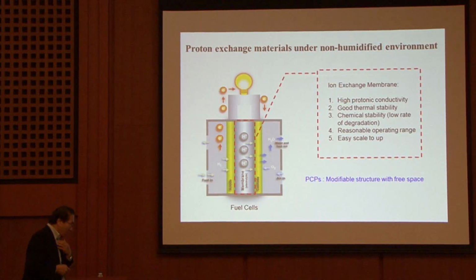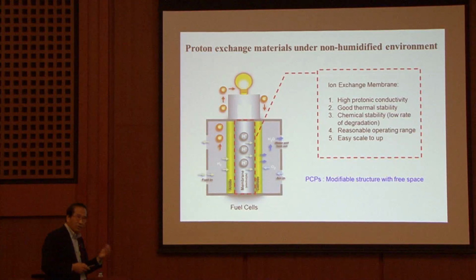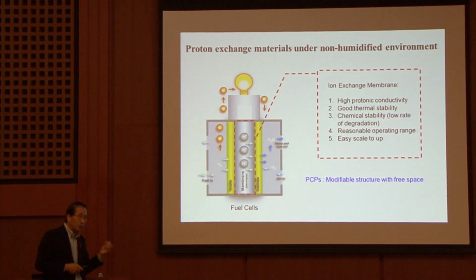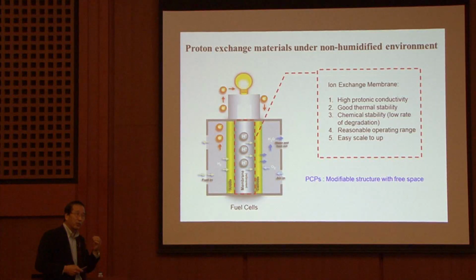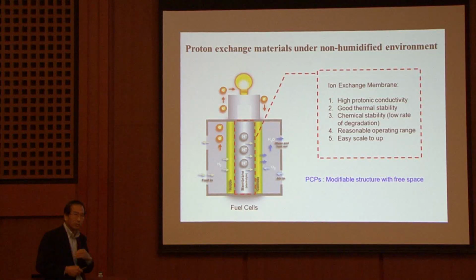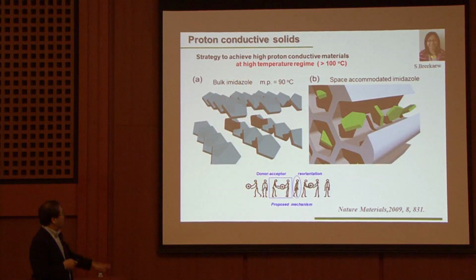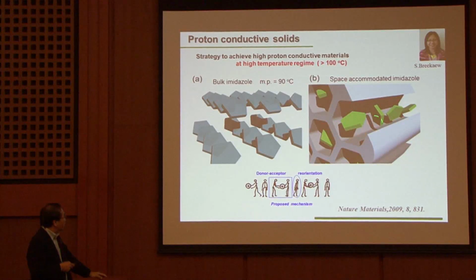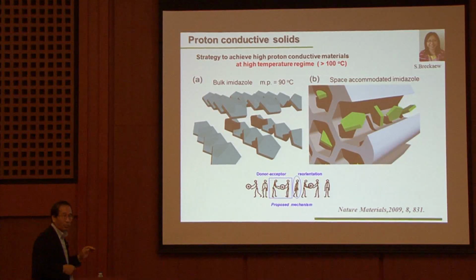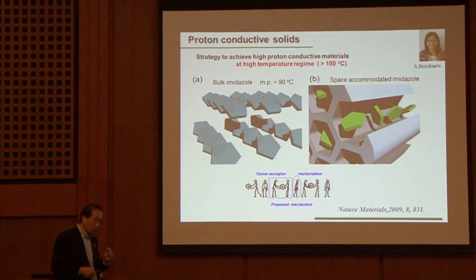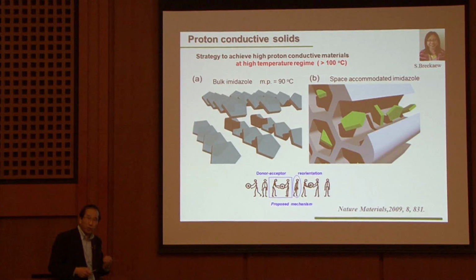Our focus is just anhydrous proton exchange materials. So we don't need to have water. By using this, we can carry out this kind of materials at higher temperature, higher than 100 degrees Celsius. So our idea is like this. We need to have this kind of molecules in the cavities. So what happens in this case? We have chosen imidazole because imidazole has the tautomeric form, proton acceptor and donor.